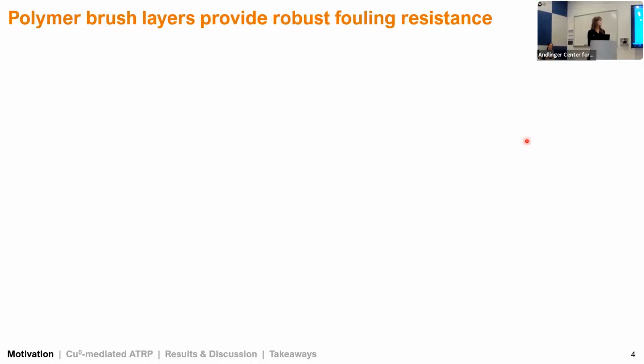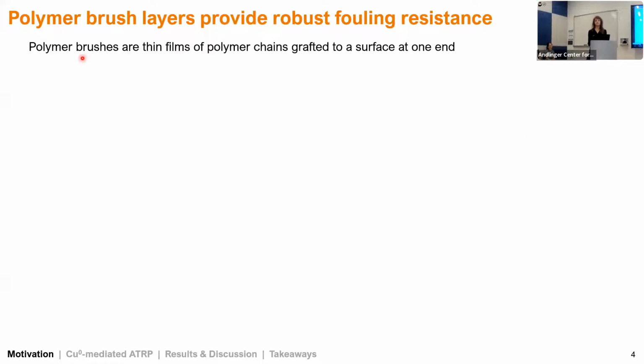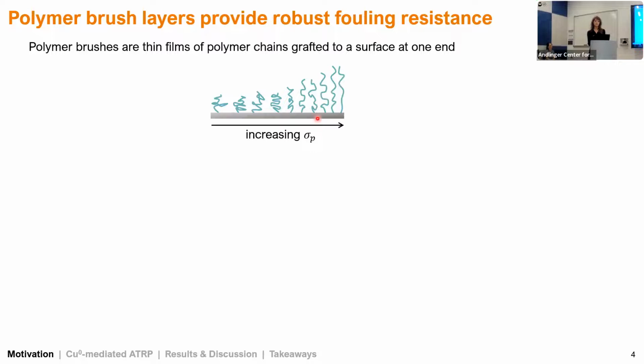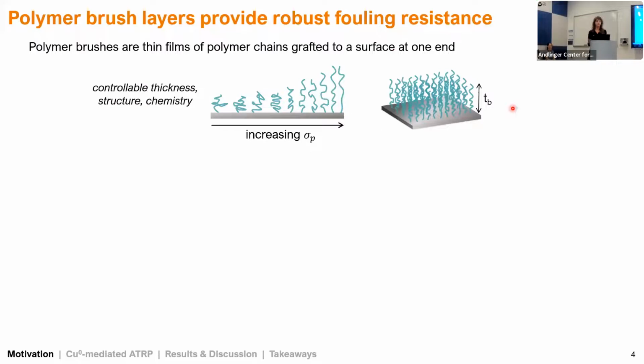Okay, so the anti-fouling material that I've been working on over the past year that I'll talk about today are polymer brush layers. Polymer brushes are thin films of polymer chains that are grafted or covalently bound to a surface at one end. As illustrated here, as we increase the grafting density of our chains, they're sterically hindered and they're forced to extend outward from the surface. And that results in this kind of brush bristle-like layer that we see here, where TB indicates the thickness of our brush. And we can control the thickness and the structure and the surface chemistry.